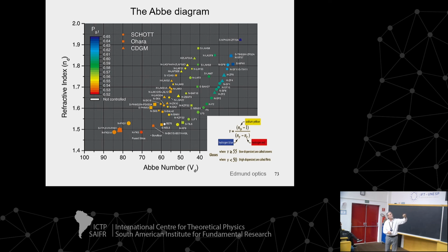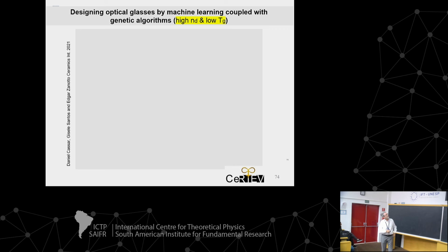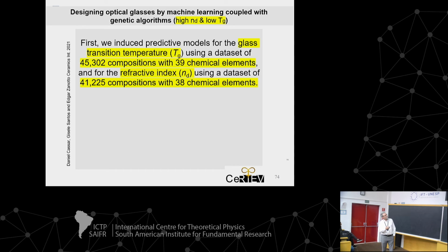These are the commercial glasses. I want a new glass for my equipment. Then I can do a training. We did that for TG and for refractive index, using 45,000 here, 41,000 here. 38 chemical elements here, 39 chemical elements here. This is what we gather from the literature.